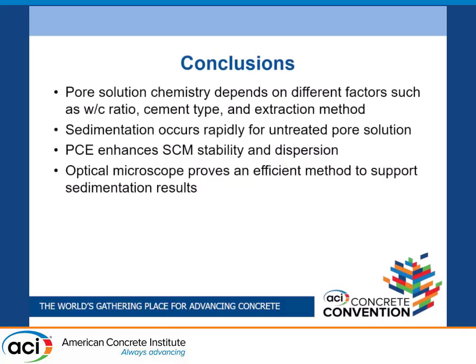From this study, we get the following conclusions. First, pore solution chemistry depends on different factors such as water-cement ratio, cement type, and extraction method. Second, sedimentation occurs rapidly for untreated pore solution, and we concluded that PCE enhances the stability of the supplementary cementitious materials. Another conclusion is that optical microscopy proves an efficient method to support the sedimentation results.